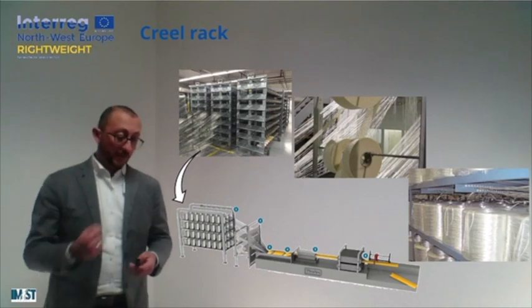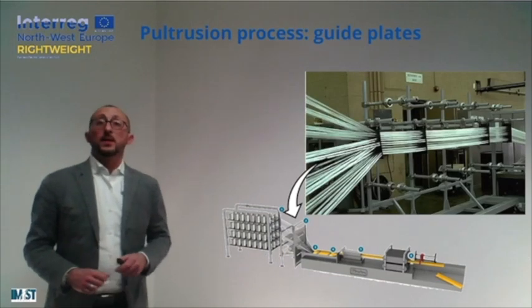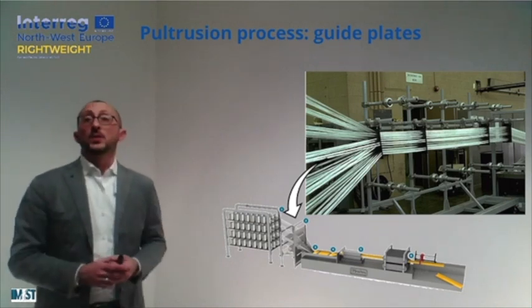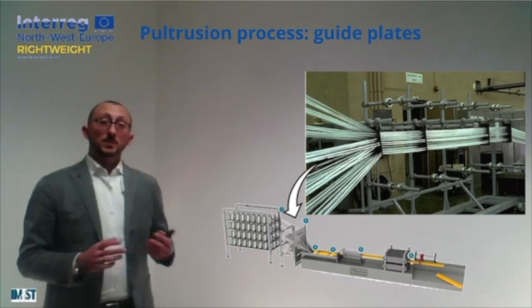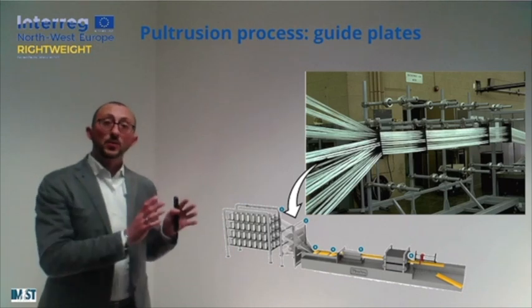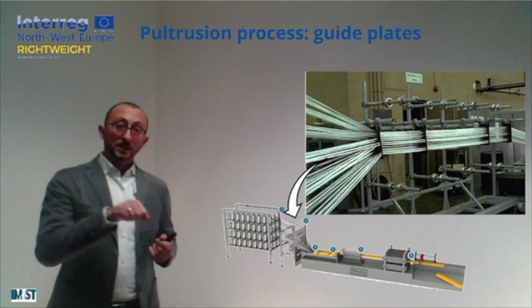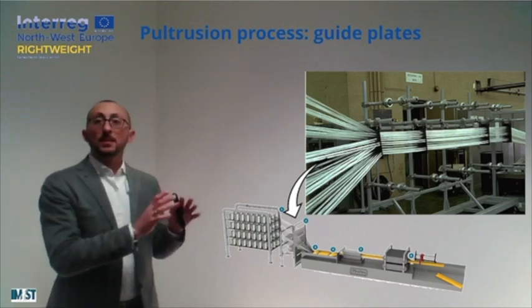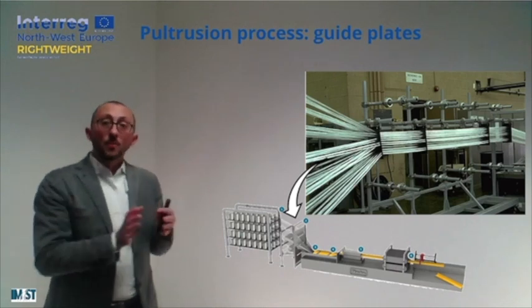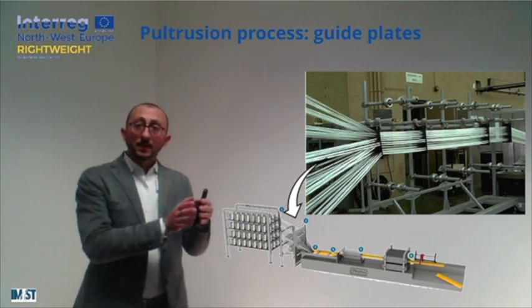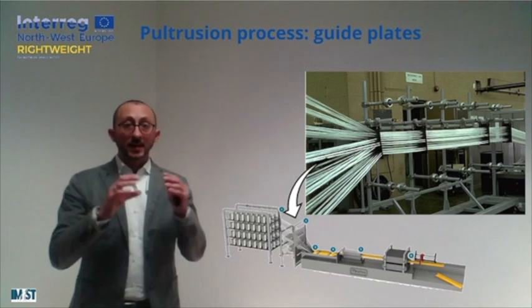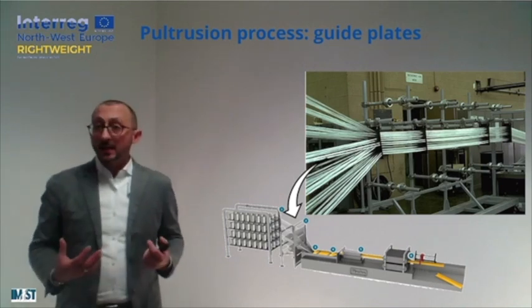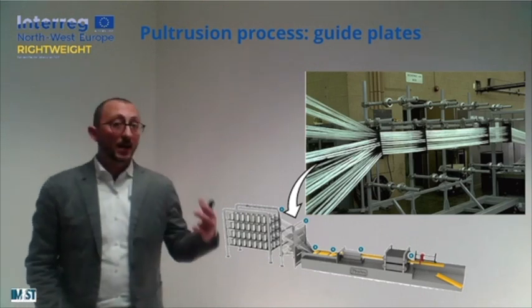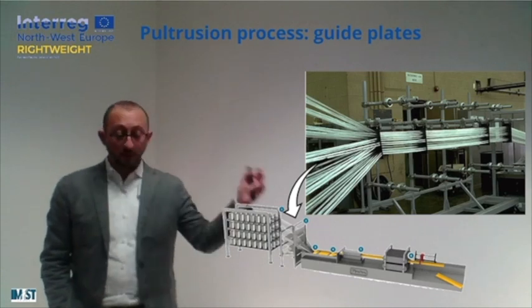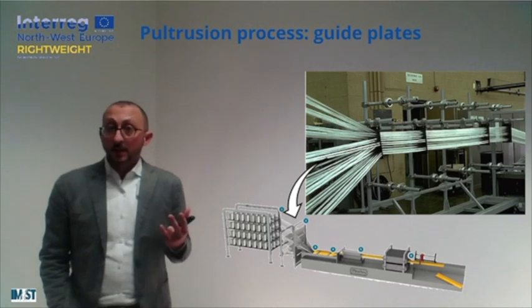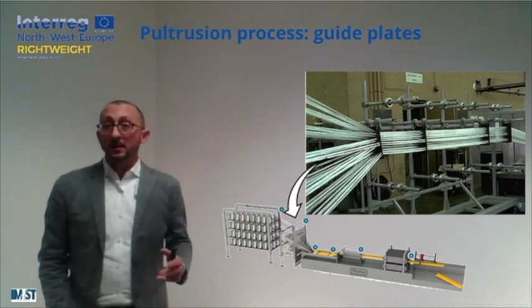Our reinforcement, just pulled out from the creel rack, will start some kind of preforming using the so-called guidance plates. These plates are drilled, and through each hole a group of fibers is passing in order to start some placing of the reinforcement in our cross section. So moving slowly, plate after plate, and following this kind of material collimation, organization of the reinforcement in our cross section. Once again, this is very important in order to avoid any mechanical interlocking of the fiber and keep with our process that virtually can produce a never-ending profile.